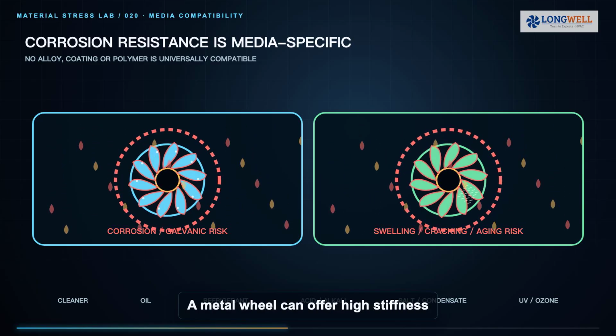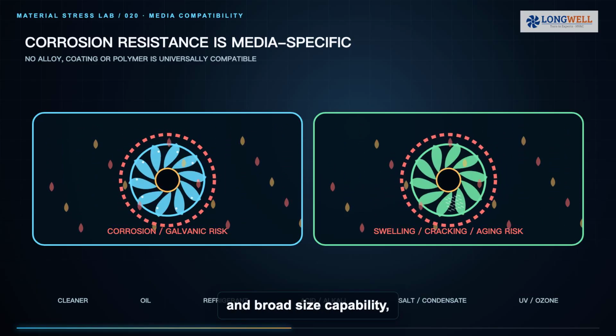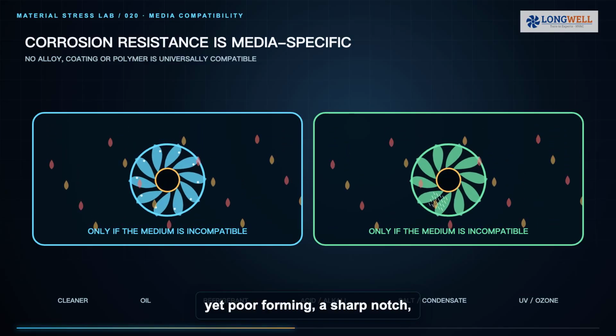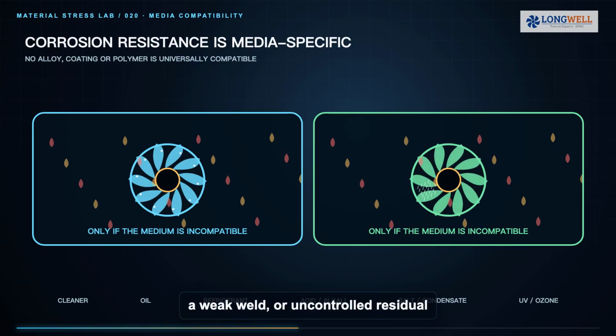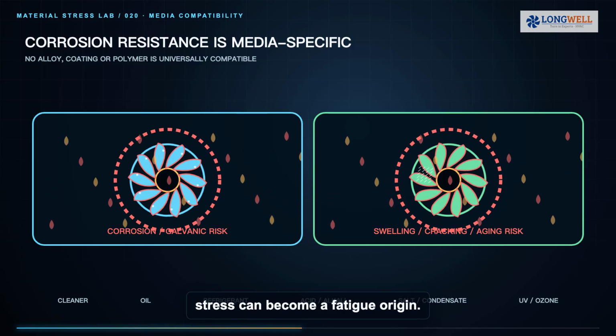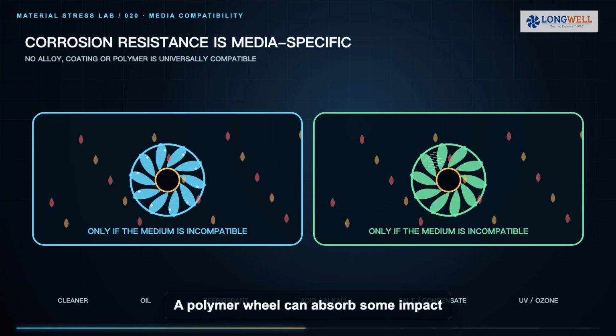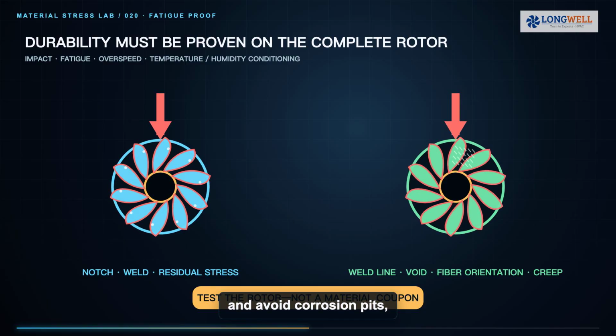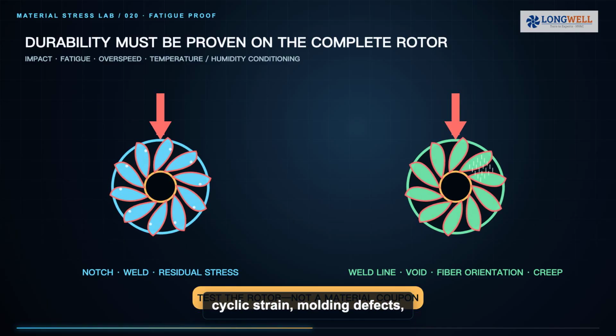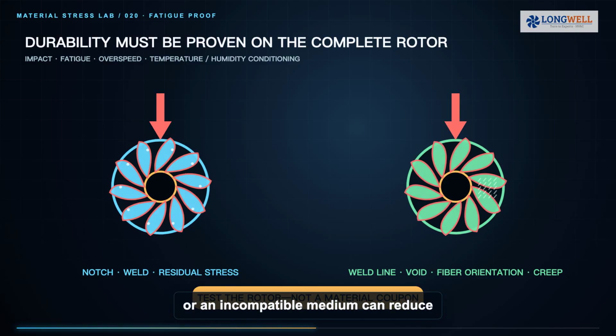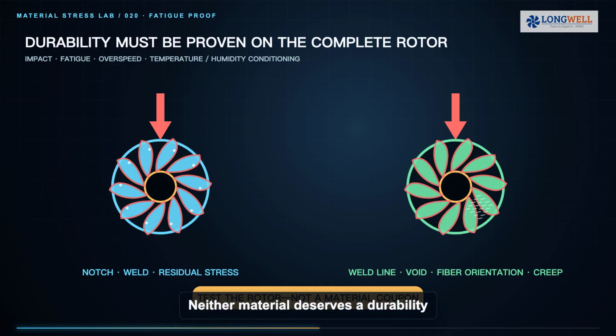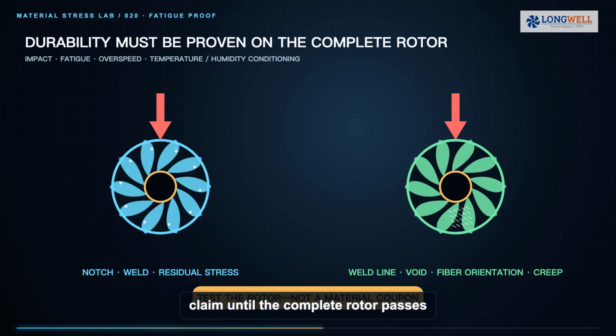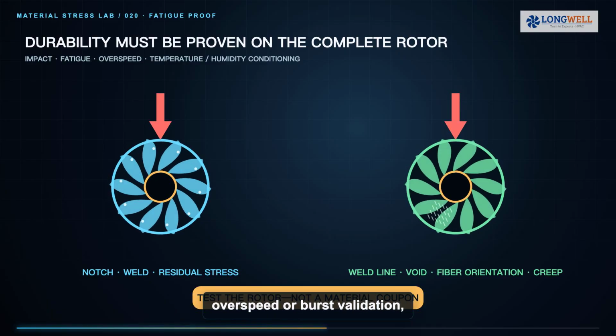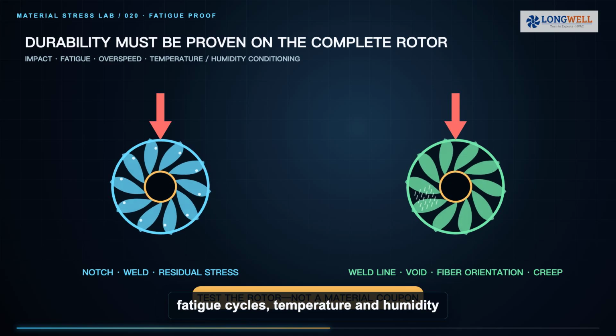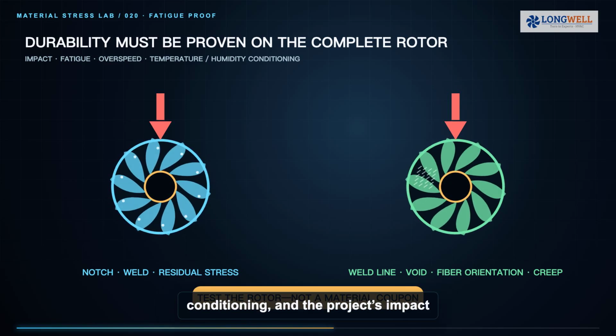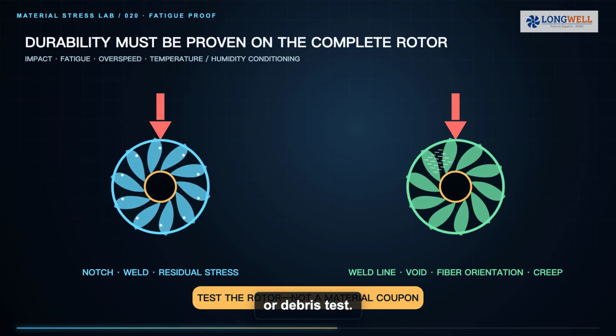A metal wheel can offer high stiffness and broad size capability, yet poor forming, a sharp notch, a weak weld, or uncontrolled residual stress can become a fatigue origin. A polymer wheel can absorb some impact and avoid corrosion pits, but long-term creep, cyclic strain, molding defects, or an incompatible medium can reduce margin. Neither material deserves a durability claim until the complete rotor passes overspeed or burst validation, fatigue cycles, temperature and humidity conditioning, and the project's impact or debris test.